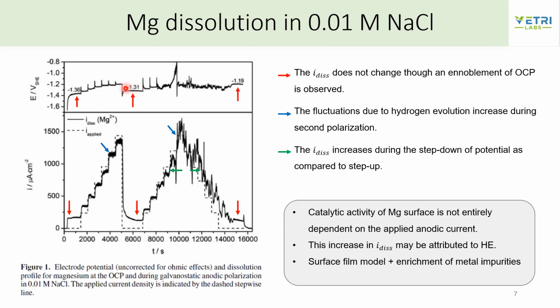The second thing that they observed was the blue arrows, which is the fluctuations due to hydrogen evolution. When they were measuring the dissolution current for magnesium, they could not measure the hydrogen evolution. So it was either the magnesium dissolution or the hydrogen evolution - in this case, they just measured the magnesium dissolution.